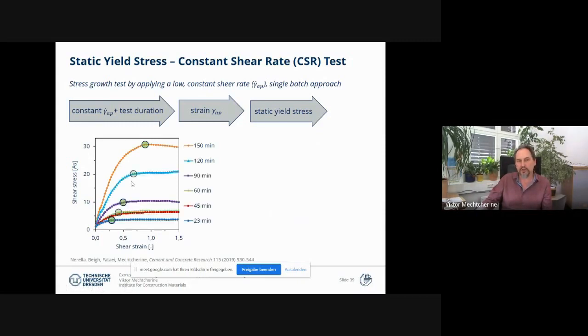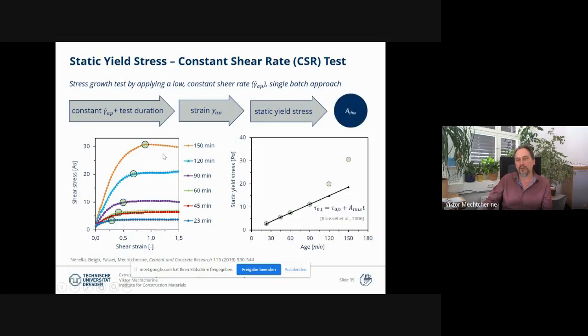And then we can perform these experiments at different times after mixing the concrete, and then you can read here the maximum, and you can also deliver the development of the yield stress in time. Usually for the first hour or maybe a little bit longer, you get a linear relationship. If you go further, due to progressive hydration, you usually get an exponential increase. So these two formulas are most often used to describe the material behavior in the first hours.